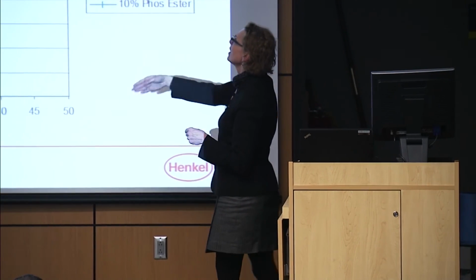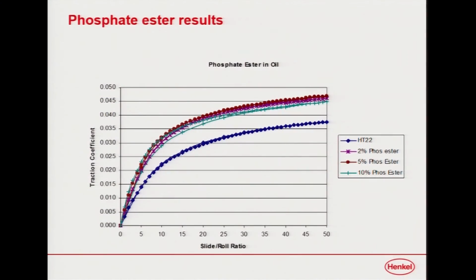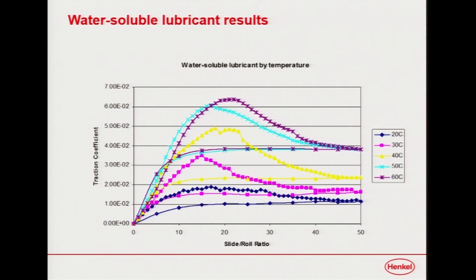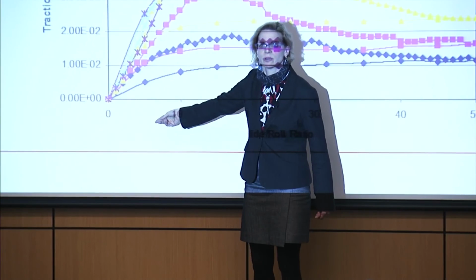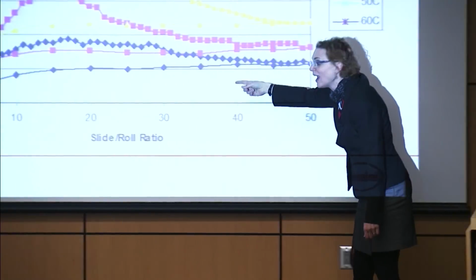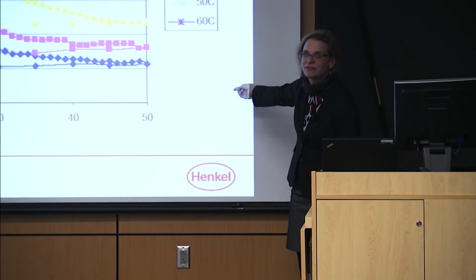What's interesting was when we started to look at the phosphate esters in the oil, now those had a very poor correlation coefficient, of course. When we put them in a pure white oil, there was not a whole lot of deviation, and they behaved very hydrodynamically. But when we put them in water, this is called hysteresis. Hysteresis means going in one direction is very different than going in the other direction. And if you look at the traction coefficient, it goes up. What happens when it goes up? There's more friction. And when there is more friction, there is more heat. And when you get above a certain point, it starts to come back down. Why? Because you have gone over the activation energy barrier.